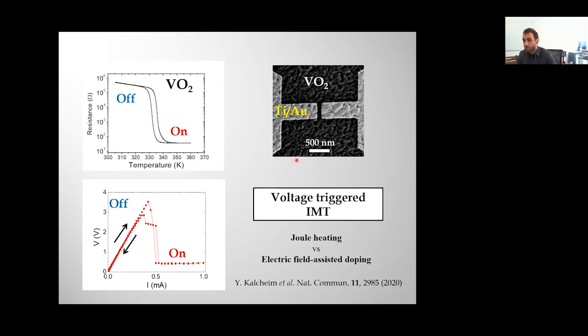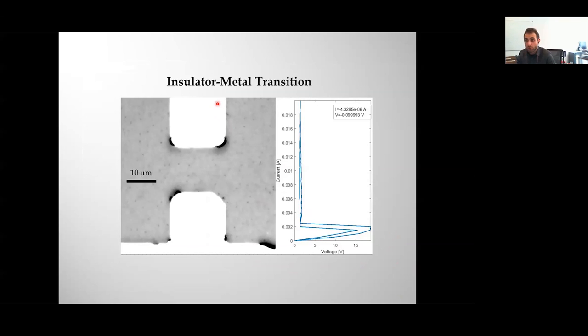So why is this happening? The most straightforward answer is it's just happening because of heating. You're just passing a current and you're heating up and you're going into the metallic state just because you're raising the temperature. But we discussed here, I won't go too much into this, that this is not the only mechanism. Actually, for example, in VO2, there is a very strong direct effect of the electric field, which we see can produce electric field assisted doping and stabilize the Mott insulator and produce a transition into the metallic state. But you can find the details here. So how does this look spatially?